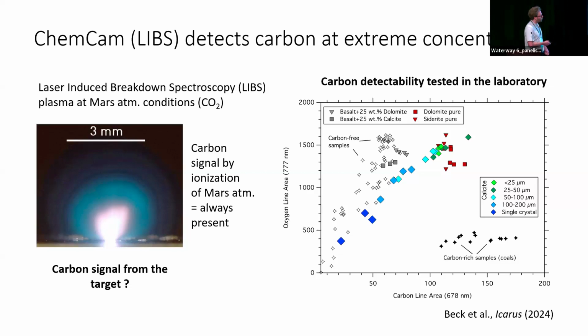We tested that in the lab. This is a paper recently published, right in time. We got lucky on that. By Pierre Beck. Here you see carbon and oxygen, so you see the two go together on a carbon-free sample. But when we shoot at carbonates, you see that some pure carbonates can have a distinguishable signal. But if there is only 25%, you see it's barely significant.